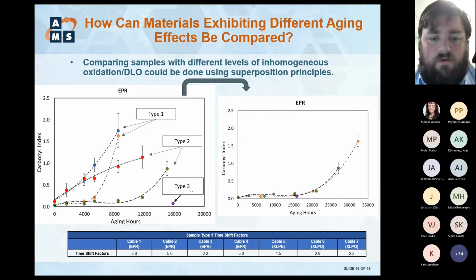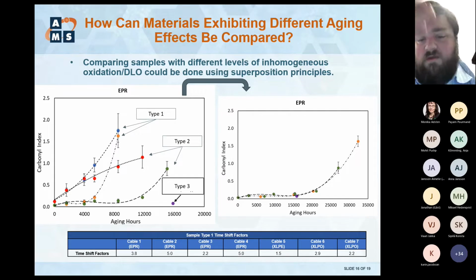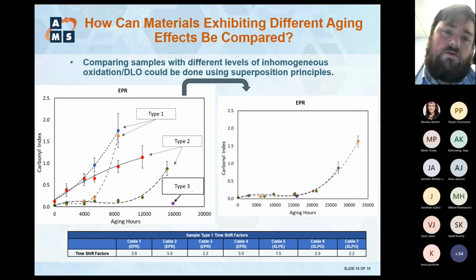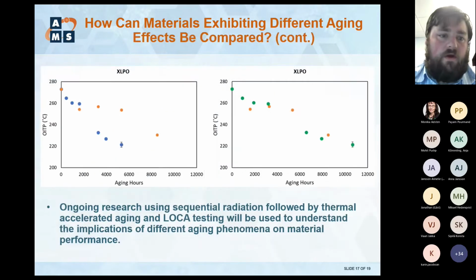And doing that, we came up with shift factors in that case, or time shift factors essentially. What we use those for is, okay, if you take an EAB value of a type 1, how do you relate that to electrical properties of a type 3 or something like that? If you're just looking at DLO effects, this is one method that we've tried to use. We're still refining it because there are differences you would expect. This is not a tried and true way of doing it, but it is an approach we have used for some of our data to relate one type of data to another, one type of material to another.